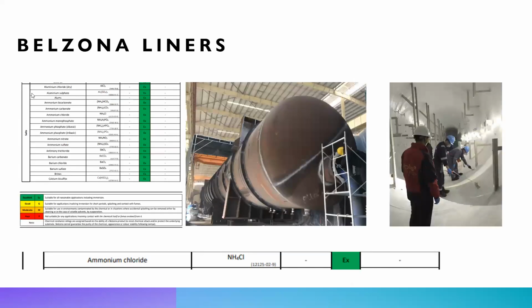So going into ways to prevent it, Belzona liners, if we can handle the surface, we are resistant to ammonium chloride. So typically salts are corrosive towards metals. However, salts are not very aggressive towards non-metallic coatings such as epoxies. So you'll see we have a lot of testing versus salts.